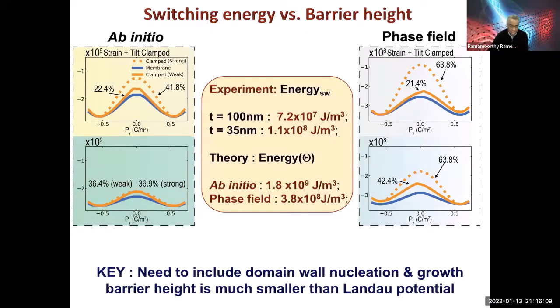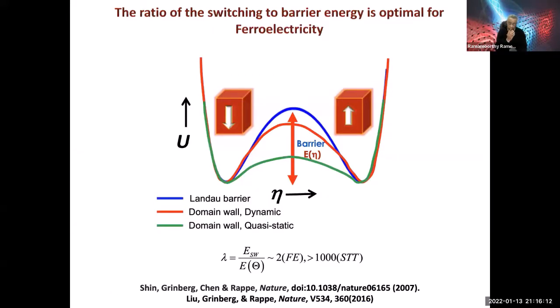I think I've said enough about this. I will just say that Wolfgang knows a lot about this, and we've had huge discussions about it. I just want to summarize this whole business. If you look at what happens during switching, the blue curve is a so-called Landau switching behavior. That is equilibrium, of course, and it's saying that you have to switch the dipoles coherently. In many cases, you don't have that. You have domain wall nucleation and growth, and you have something that looks like the green curve, which I call domain wall mediated, but quasi-static, meaning at very, very low frequencies.